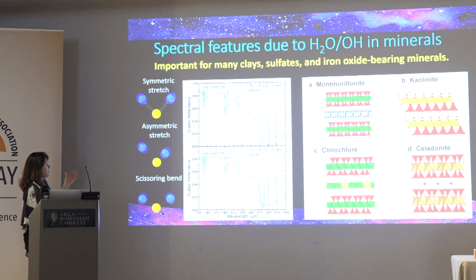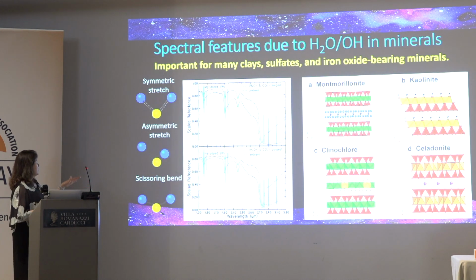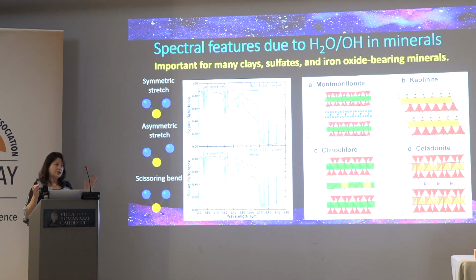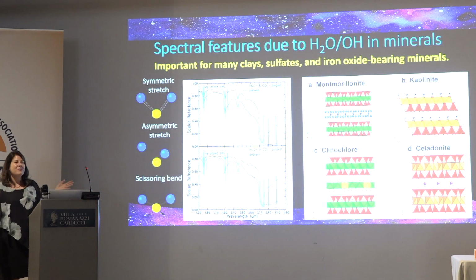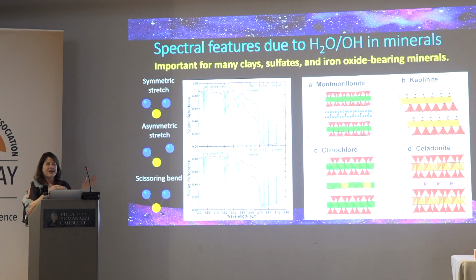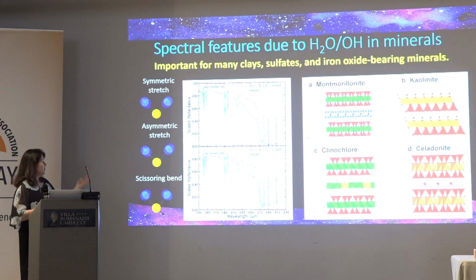and we were looking at spectra measured under ambient conditions and spectra measured under moist, humid conditions, and I marked the water bands in blue and the OH bands in green, and these are combinations and overtones. So there's a symmetric stretch and an asymmetric stretch and some bending. So these mid-infrared vibrations are then added up in combination bands or as overtones.